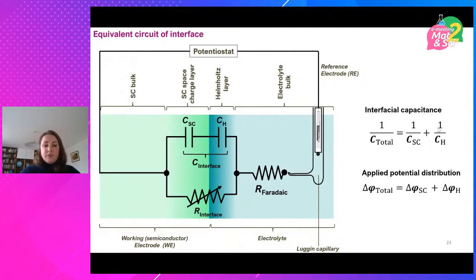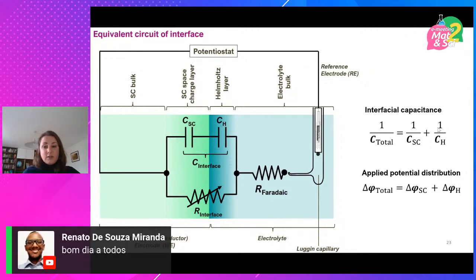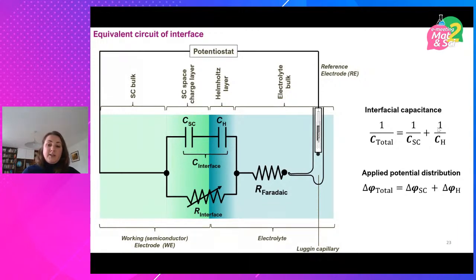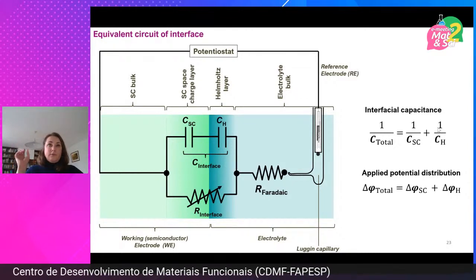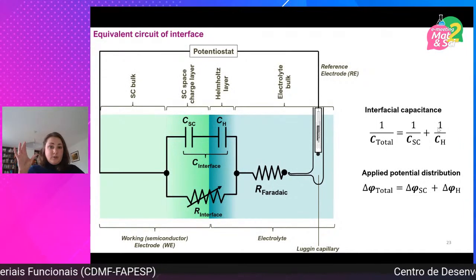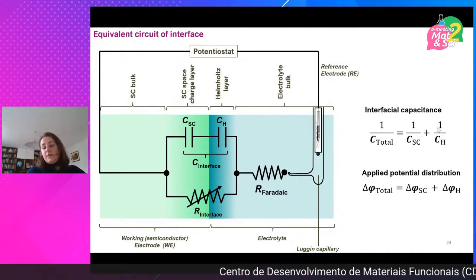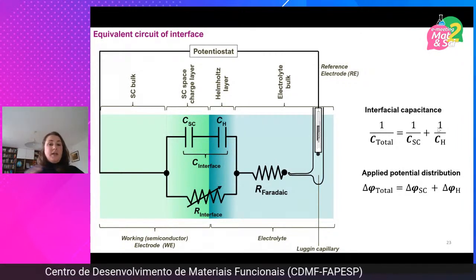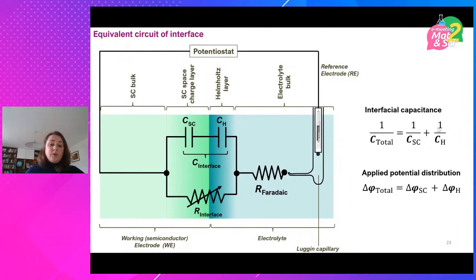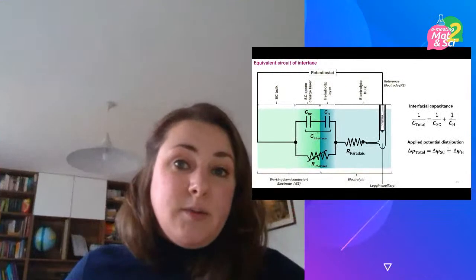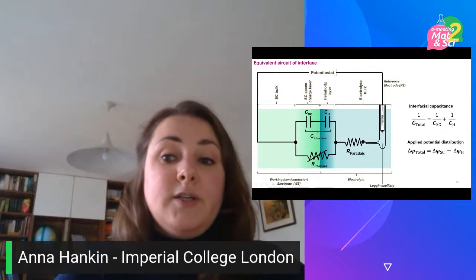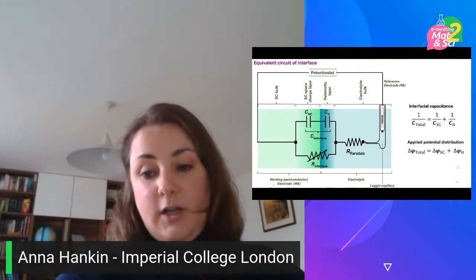And the other aspect is that it's often assumed that all of the applied potential is dropped across the semiconductor space charge layer, because the electrolytes are concentrated, and so there shouldn't be a significant drop across the Helmholtz layer. But again, when we think about what happens at a metal-liquid interface, a metal is a conductor, right? So there is virtually no potential drop across the metal, and all of the potential drop is across the Helmholtz layer. That's how most electrochemistry that doesn't involve semiconductors works. So when you have a poorly doped semiconductor, yes, the Helmholtz layer doesn't get a high drop across it. But when we have the kinds of semiconducting photoelectrodes that are being developed these days that are quite highly doped, a lot of them are quasi-metallic, which means that it cannot be assumed that none of the applied potential goes across the Helmholtz layer.